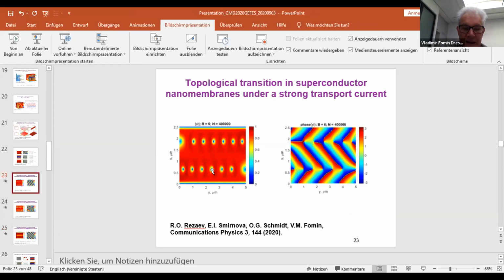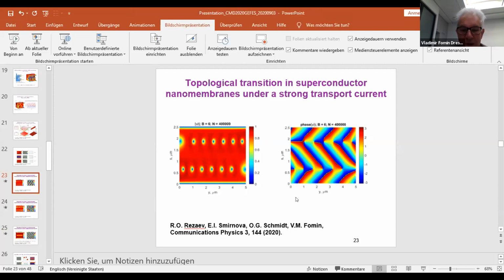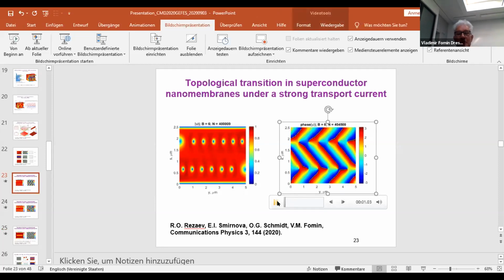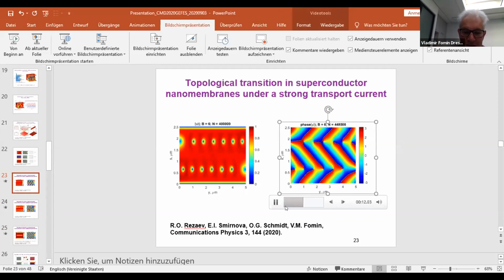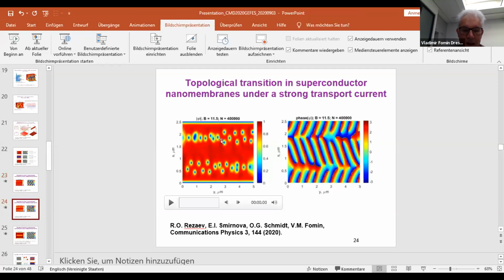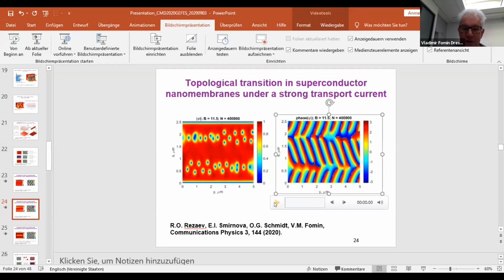Now we enter a regime of higher currents. If we have a certain magnetic field, it's 6 millitesla, we have such a picture of moving vortices, which is confirmed by the estimation of the change of the argument around these topological defects. Now we increase the magnetic field twice. And here we must have already almost two chains. And this is again supported by calculation of the phase.